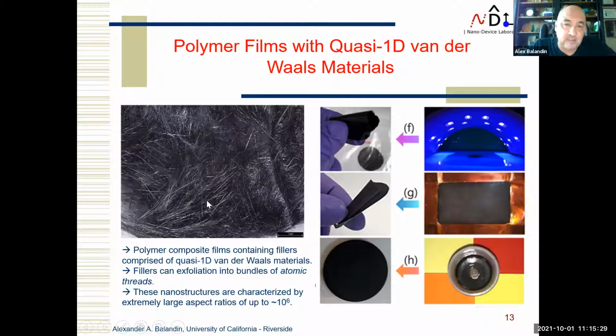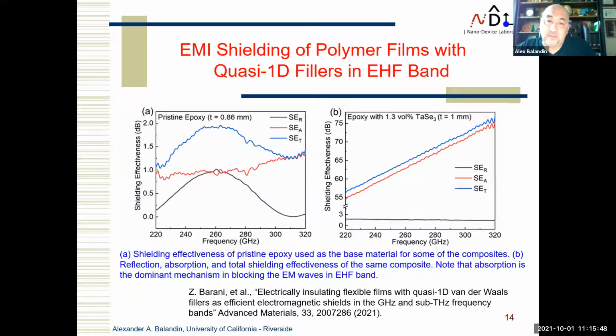So what you see on the left is this material, and you can notice needle-like structure of crystals of these materials. Because the aspect ratio of these materials could be extremely high, and there is no problem, like in case of carbon nanotubes, with control of what type of conductivity there, it performs amazingly great as a filler for electromagnetic interference, EMI, shielding. In this particular case, we managed to make an electrically insulating film, which was soft, yet it absorbs electromagnetic energy extremely well, so it can work as an EMI shield, both in gigahertz and even sub-terahertz ranges.